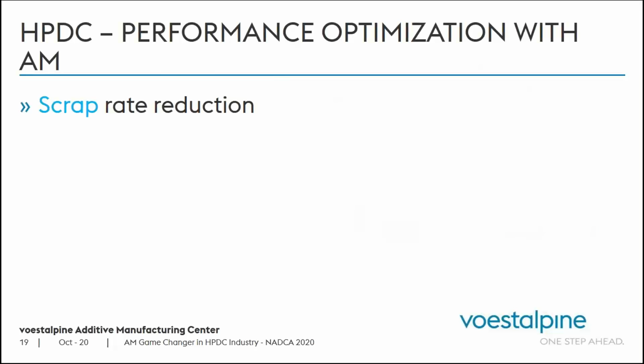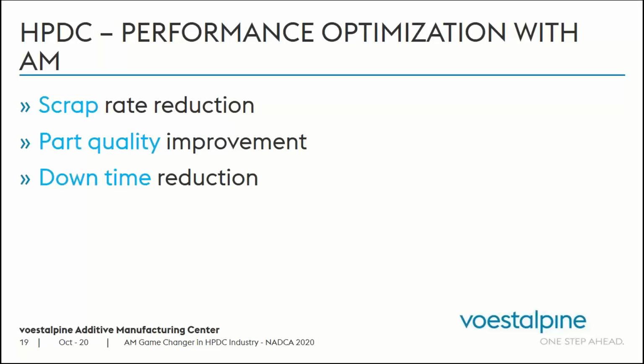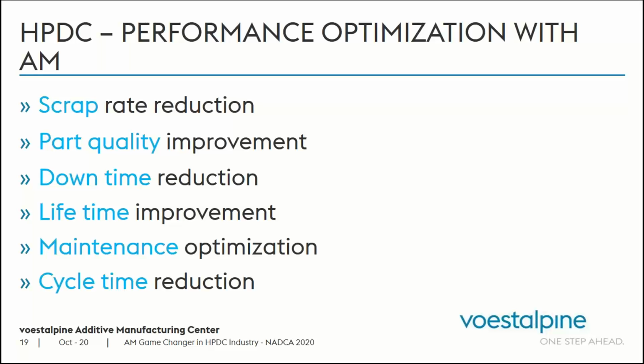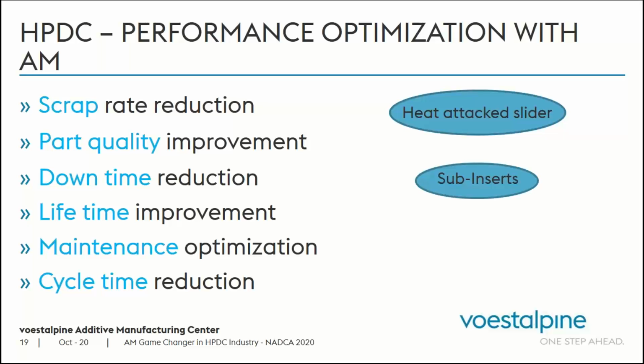So for optimizing high pressure die casting by additive manufacturing, it adds value by reduction of the scrap rate, which is very common and very costly for the die casters. Part quality improvement, this is value added by using additive manufacturing. The downtime reduction and the lifetime improvement, maintenance optimization, and last but not least, cycle time reduction. And the categories of groups of parts that could be improved by additive manufacturing are heat attacked sliders, sub-inserts, and the distributor or ring as well.